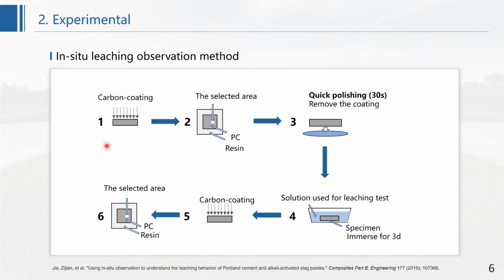Here is the in situ leaching observation method we used in our study. Firstly, the surface of the sample before leaching is coated with carbon to enhance the conductivity. Then, certain areas containing representative phases are selected and marked on the BSE, and EDS is applied to analyze the composition of these phases. After the analysis, we will use quick polishing to remove the carbon coating layer on the surface of the sample.